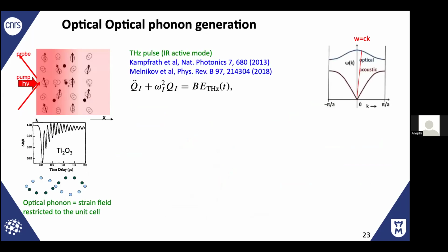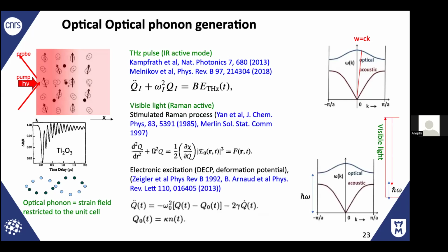So for optical phonons, this is the most direct, which is quite recent, because now we have THz, or large enough intense infrared lasers that can give rise to direct coupling between the THz electric field and an infrared active mode. So this is possible. And as you also know, with visible light, with stimulated Raman, when you typically pump below band gap, even if you work with a virtual state, you modify the electronic cloud, you still polarize the system transiently, and in that case, through the Raman tensor, you can generate optical phonons. This is basically the case in that titanium oxide material.